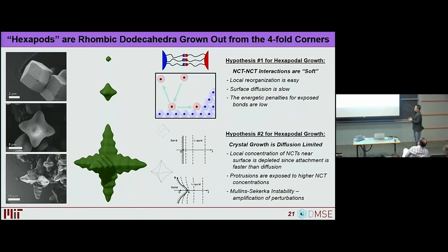And because those fourfold corners are pointing out into solution just a little bit more, those are the structures that actually propagate. So it's not so much that we have something that was a rhombic dodecahedra and it transforms into this, it's more that once we get to a certain size, the driving force for turning this into a rhombic dodecahedra goes away. What that basically tells us is that it's less about the crystallographic symmetry or any of the vectors of crystal growth that are mattering in terms of crystal shape. It's the underlying crystallite shape itself, which is sort of an unusual thing to think about in crystal growth.